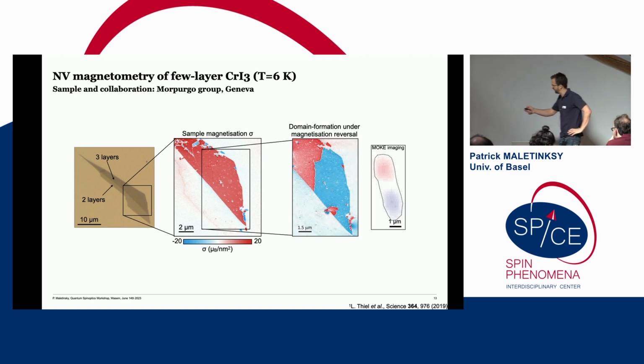And you can compare this now to this image I've shown you before, this magneto-optical Kerr effect, and I hope you appreciate right away the increase in spatial resolution, but also the quantitative nature of this image. Note that the color bar here is really in spins per nanometer square. That's the quantity you're oftentimes interested in. So this was the basis of our experiments.